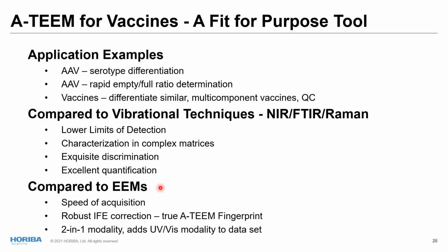So compared to EEMs as well, because I think many people have tried EEMs and maybe not been satisfied with the results, speed of acquisition is very high. We have that very robust IFE correction to get what I would consider a true A-TEEM fingerprint. And I didn't dwell on this a lot, but this 2-in-1 modality, adding UV-Vis information to a set, allows us to get a handle on discrimination that fluorescence might not. So even though I mentioned that some of the components do not have native fluorescence, and again, this is native fluorescence, we can often distinguish them by their UV-Vis signature. So this gives us essentially 5 different metrics in order to evaluate differences between samples.